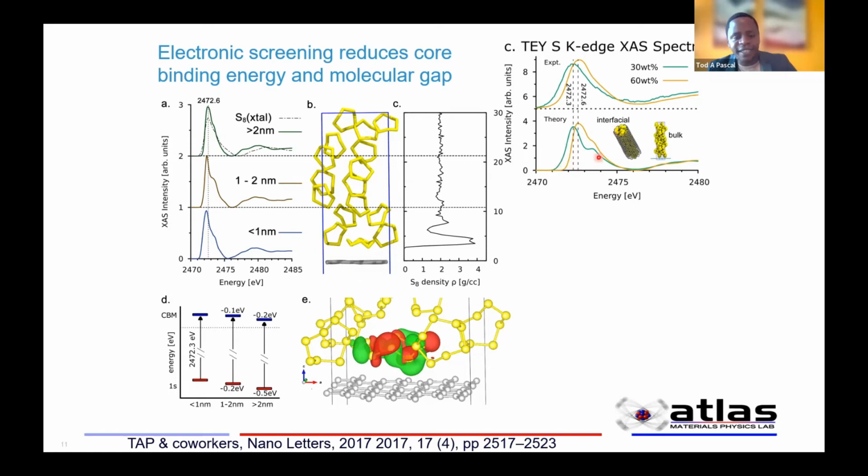So for this particular sample, the average pore size here was about maybe a nanometer to a nanometer and a half. So these were really, really small pores for these carbon nanoshells. Okay. And so most of those would be actually interfacial sulfurs, which is why you're able to get the signal. Yeah. Perfect. Now I understand. All right. Seeing no more questions, pardon me, you should continue.